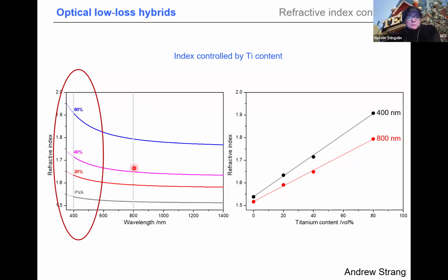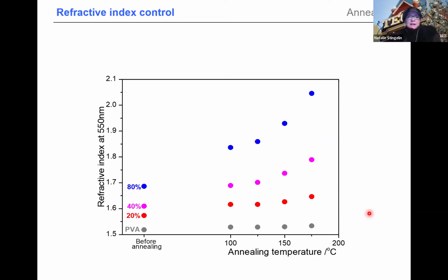Why? Independent of where we take the different refractive indices and plot it against volume content of the inorganic species, we have a very nice linear relationship. So the titania polymer are really very homogeneous. It's one structure, one material.